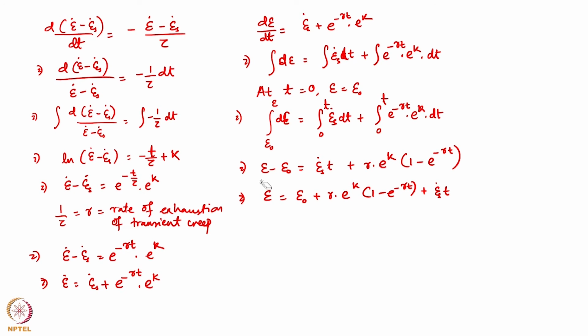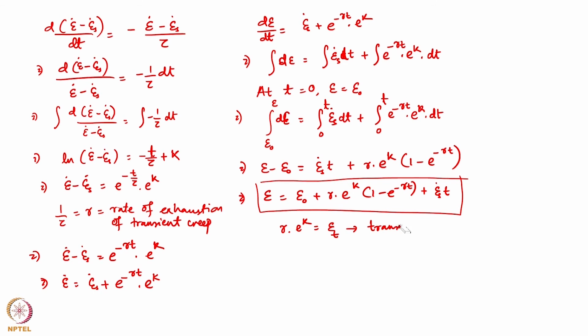The equation that we have arrived at following this derivation is very similar to Garofalo's equation, and if you notice, r into e to the power k can be written as epsilon t, which is the transient strain. Then this becomes the Garofalo equation: epsilon is equal to epsilon naught plus epsilon t into (1 minus e to the power minus r t) plus epsilon s dot into t. So, this is how, using the first order kinetic approach, one can derive Garofalo's equation.